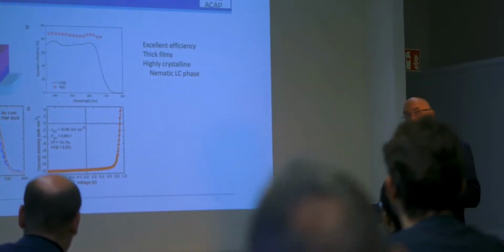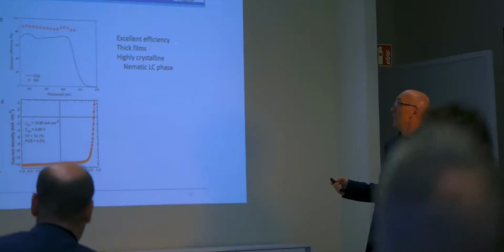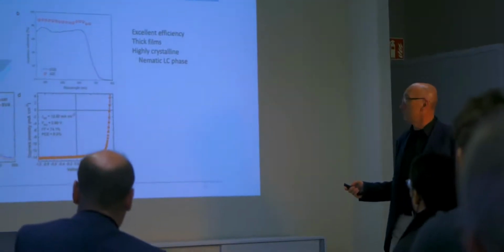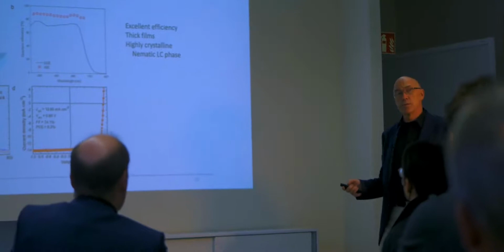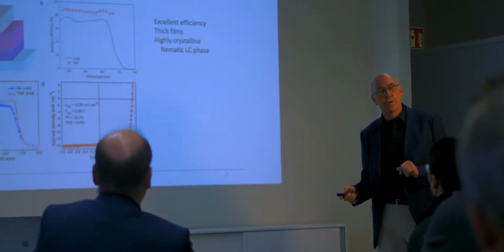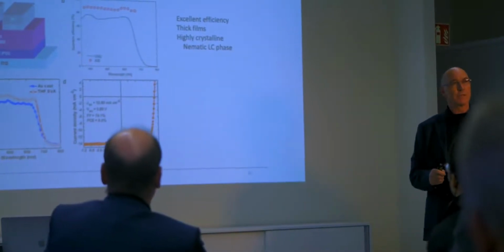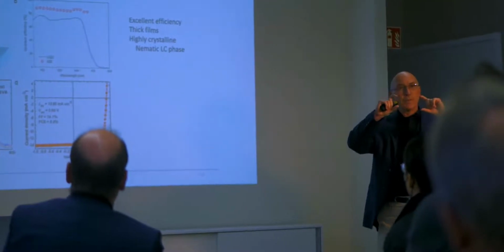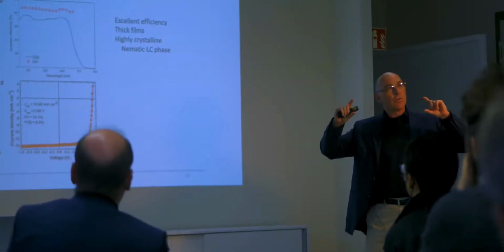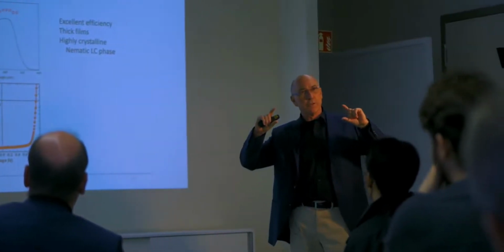And the other thing we can take away from it is they have excellent efficiency. This is back in 2015. They also worked in thick films. And this is very, very important because if you are printing a solar cell and your printing thickness varies, you don't want that to impact your overall efficiency of your cell.